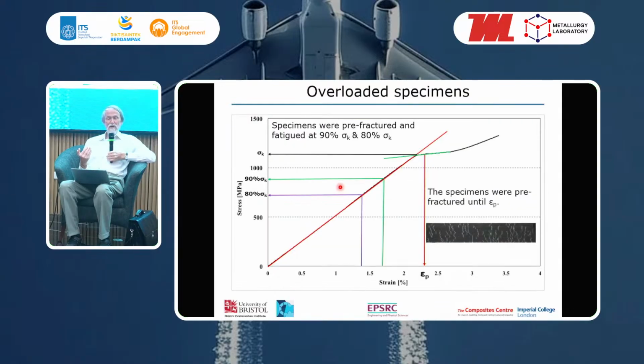Well, what happens if we overload the specimens? So you can imagine a situation where we go beyond that knee point straight in static loading, in which case, in this case here, you can see, because we've gone past that point, we've already got multiple fragmentations. So this has been overloaded past the knee point. What happens if we fatigue it now? Because now we've got some damage, and that damage may grow.